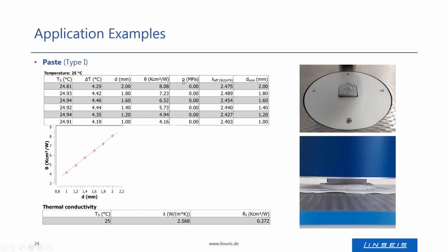Here you can see the measured thermal impedances and the effective thermal conductivity. In the graph, you can see that all those points fit very well to this linear fit, and the end thermal conductivity which was determined was about 2.6 watts per meter Kelvin.